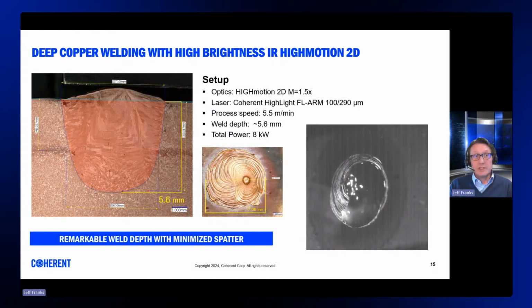Here we see a recent example of the type of results that modern advanced welding packages can achieve, with a near 6 millimeters of penetration into copper, with little or no spatter or porosity. The setup in this case combines our ARM fiber laser, operating with a combined 8 kilowatts across the ring and center beams, coupled with a high motion 2D scanner with a 1.5 times magnification. Dynamic beam wobbling is also employed to produce an impressive joint specification.